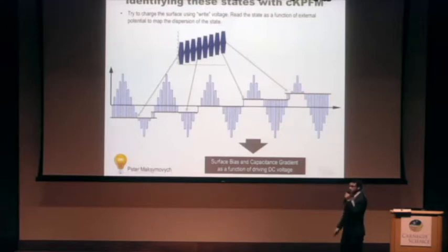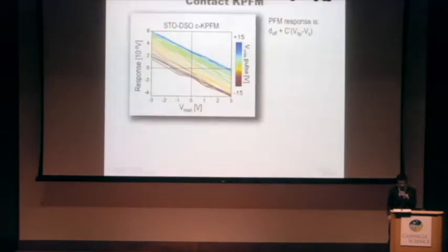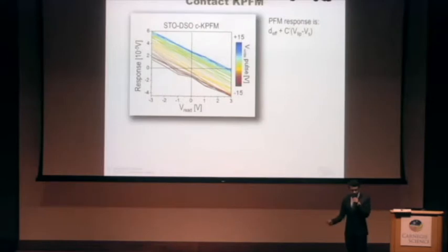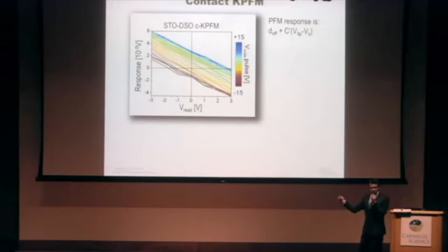And so what we hope to do with this technique is look at the dispersion in the polarization states as a function of these DC voltages. So if we take a standard material like strontium titanate as a thin film on dysprosium scandate, this should not be ferroelectric. And indeed, when we look at this response, you can see all straight lines, which suggests that this is purely electrostatic response. But let me walk you through what this diagram actually means.